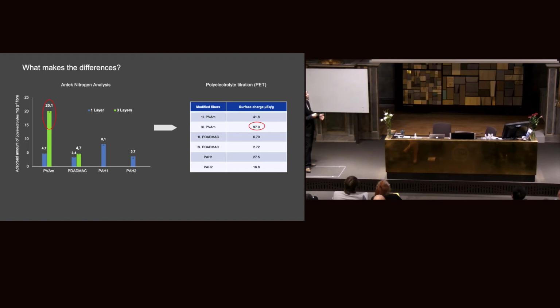So it's very important to check the surface charge of these samples. We used polyelectrolyte titration to determine the accessible positive charge on the fiber, and found that 3-layer PVAm also has a very high surface charge available for bacteria removal.